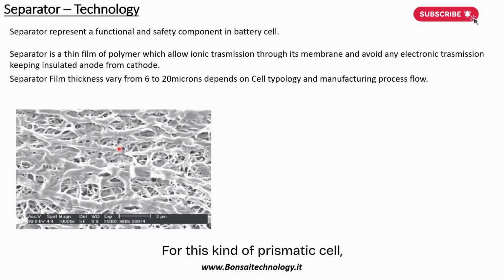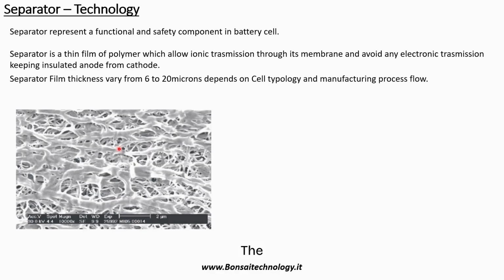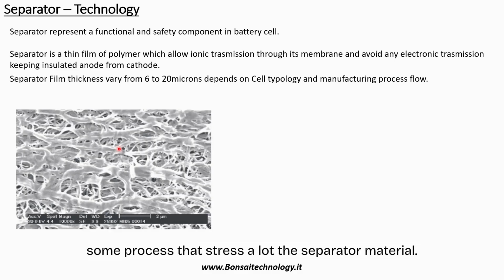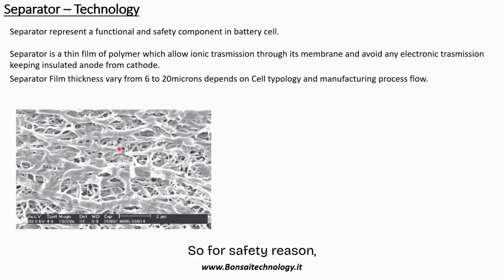For this kind of prismatic cell, again, that is done by a zip folding process that we see later on. Again, here the separator could be very, very thin, even 12 microns or 9 microns. For this kind of battery, the pouch battery, that is done through a lamination process, the separator must be quite thick, so we're talking about 15, 20 microns. The reason why is that during this manufacturing process, there are some processes that stress the separator material a lot. So the risk of using a thinner separator material is to have some internal short circuit during the working life of the battery. So for safety reasons, the battery makers are using a very thick separator compared to the cylindrical cell.